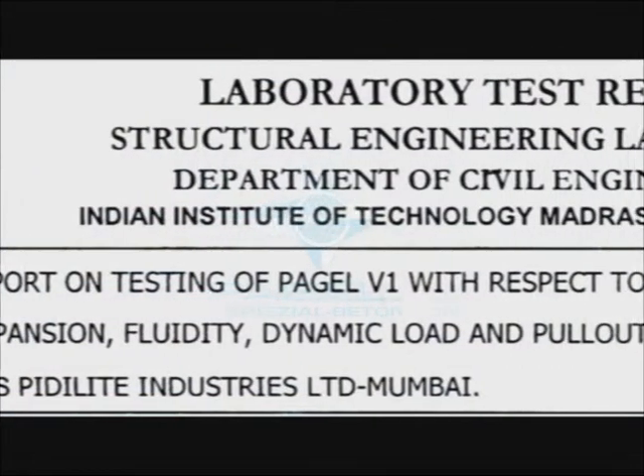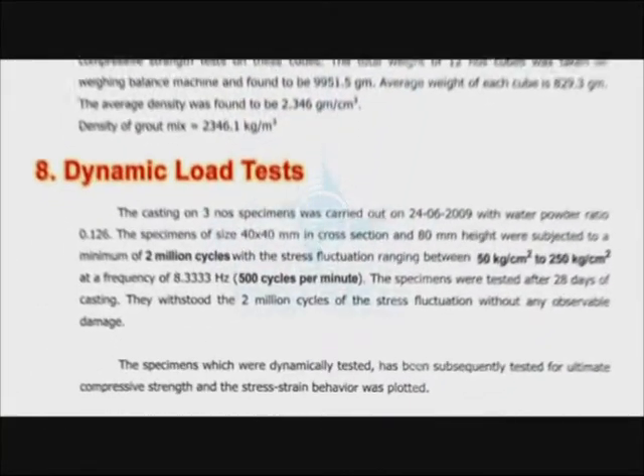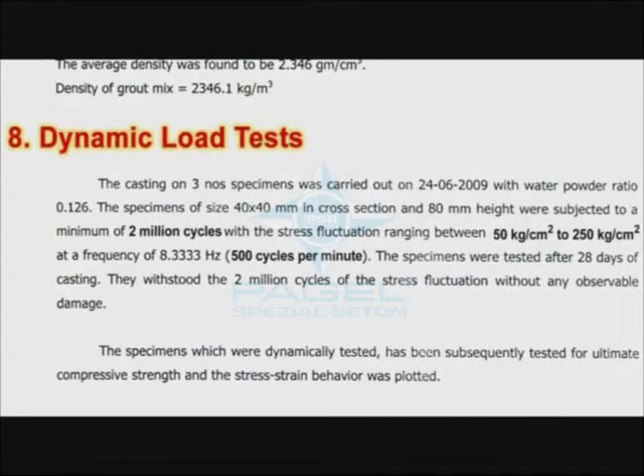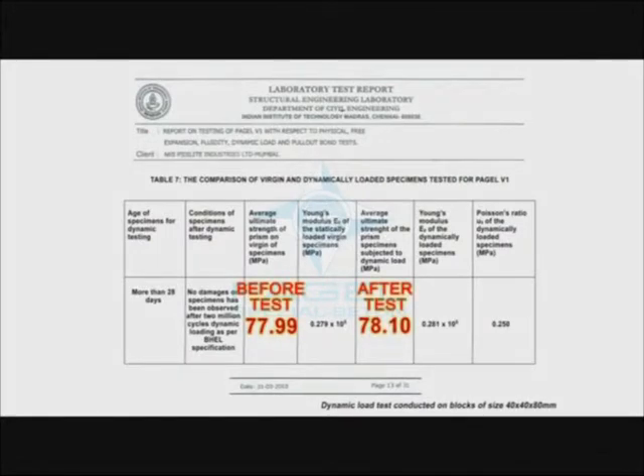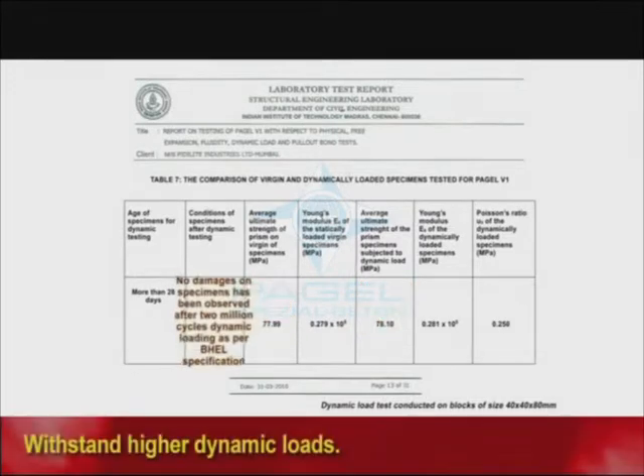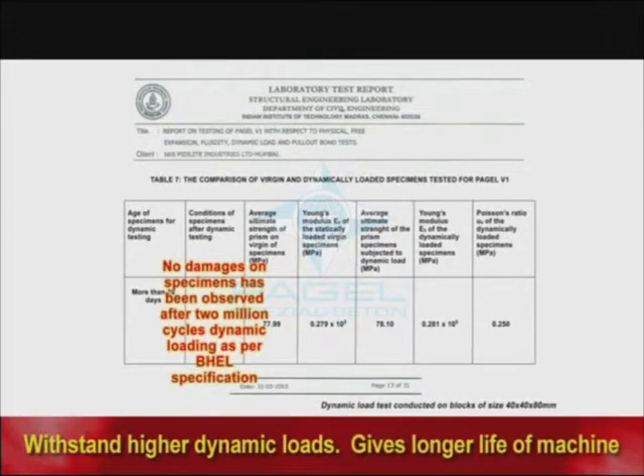The test report from IIT Chennai bears testimony to the superior dynamic load resistance of Pagel V1 grout. The grout was subject to stress fluctuations between 50 to 250 kg per square centimeter at 500 cycles per minute. Even after 2 million cycles of load variation, the residual strength of Pagel V1 grout does not drop. Therefore, with Pagel V1, your structure will withstand higher dynamic loads, giving longer life of the machine.